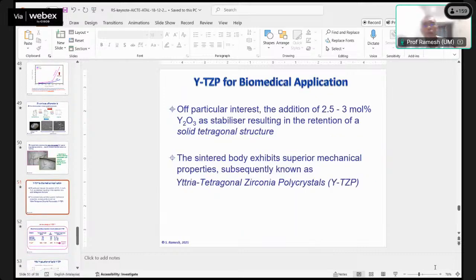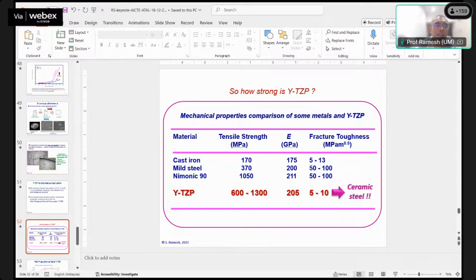Okay, so normally for biomedical application, it is the tetragonal zirconia polycrystal, TZP, or Y-TZP. Y means it's the stabilizer, stabilized with 2.5 to 3 mole % yttria. With this stabilizer, you are able to retain the tetragonal structure at room temperature and therefore the highest mechanical properties. This is some comparison of Y-TZP with some typical metal. As you can see, the Young's modulus of Y-TZP is almost similar to steel, and that's why Y-TZP is sometimes known as ceramic steel.